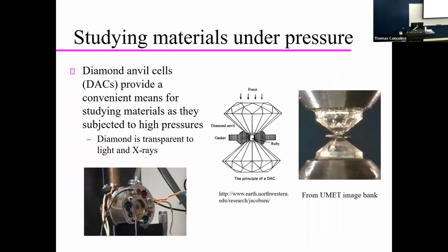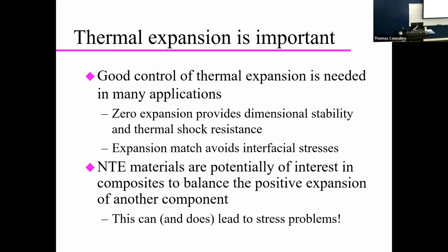Very nice. Okay, so in addition to high temperature, variable temperature experiments, which could be done in many cases in the home lab, or almost equally well if you have the right equipment, we do high pressure measurements as well. Common mode to do that is the so-called diamond anvil cell. This is a diamond anvil cell. It's about the size of my fist. At its core, we've got a pair of diamonds squeezing on a gasket, basically a metal washer with a tiny hole on it. Your sample is in this cavity. And X-rays are going to go